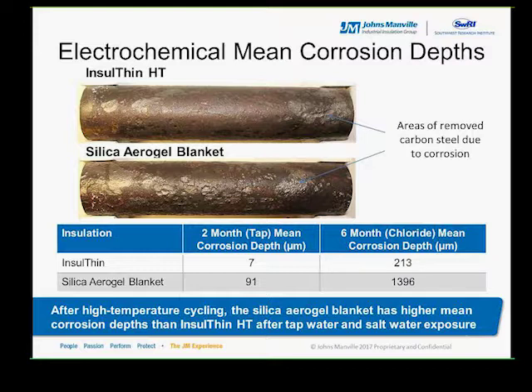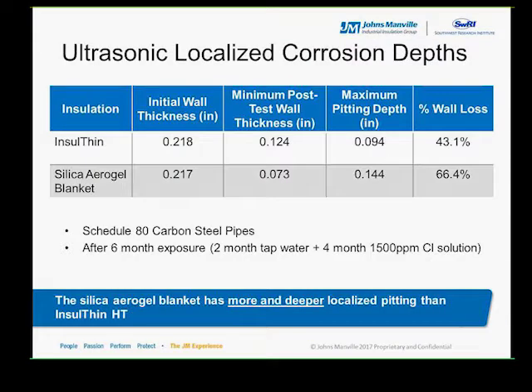So what this shows is that by changing the condition of the test environment, or in actuality, the process conditions, you can get a very large difference in the CUI results. In this example, the insulation makes a difference, but so does the cyclic heating of the pipes. If we look at the samples using the ultrasonic method, the same conclusions can be made, which is comforting that both methods show the same results.